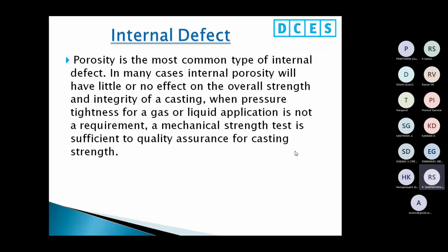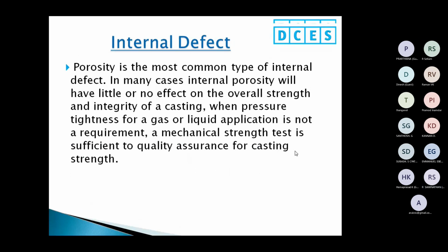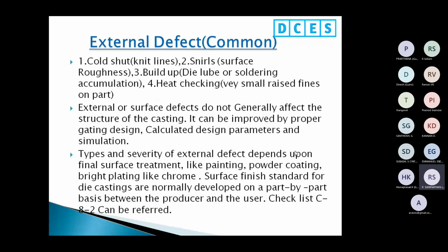The mechanical strength test is sufficient to qualify quality assurance for casting strength. Wherever the quality requirement asks for leak testing or pressure testing, it is very important to define the porosity level or internal defect. The external defects are commonly: cold shut, that is knit lines, we call it incomplete fill, snirls, surface roughness, build up, die lube or soldering accumulations, heat checking, very small raised fins on part. This is called cold shut, and other defects.